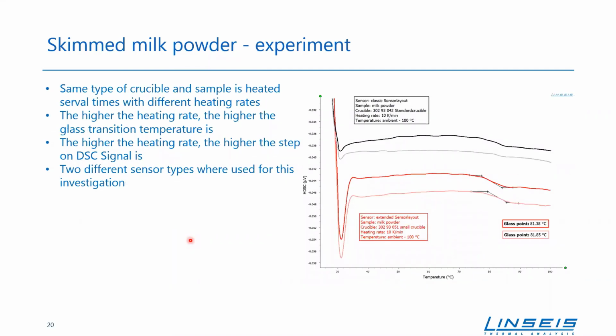So this is the result now, and what we've done here is we've compared the standard sensor, our classic sensor layout, with our high sensitivity extended sensor layout. What you can see on the right is that there's a difference, because due to the 30% higher sensitivity, we achieve much better signals for this glass transition. So this is what we want to figure out in this slide. Of course, it's possible to do the investigation also with the standard sensor layout. It's possible, but it's much easier if you use the extended sensor with a higher sensitivity. So you can see the results there.